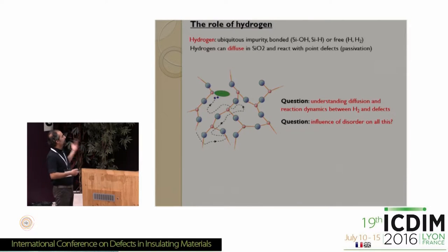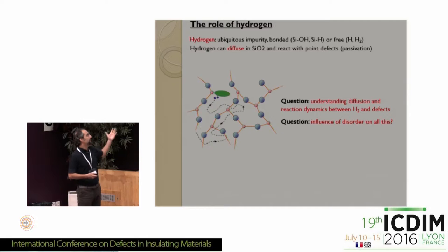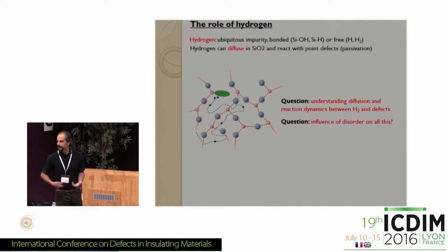And going back to point defects, this is important because this diffusing hydrogen can react with point defects and change them. For instance, as we will see later, hydrogen can react with the silicon dangling bond and convert it to SiH groups, which means you are passivating the E prime center, the silicon dangling bond, and you remove the optical absorption in the ultraviolet that the center is responsible for. So this is important from a practical point of view. And also from a fundamental point of view, once again, it's interesting to understand at the fundamental level the diffusion-reaction dynamics between hydrogen and the defects, and if there is a role of disorder in all this.